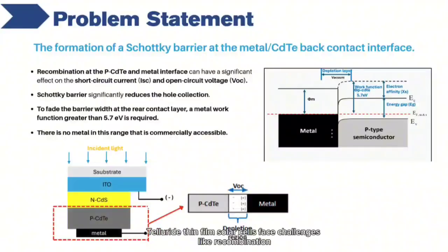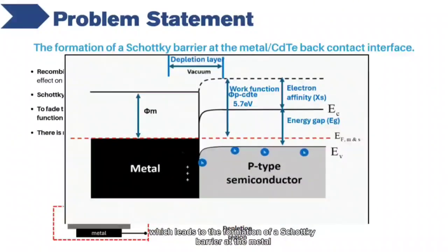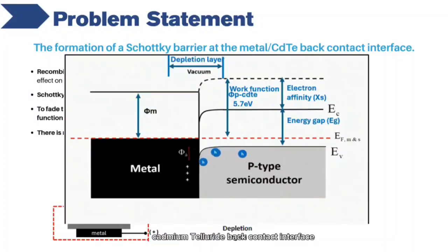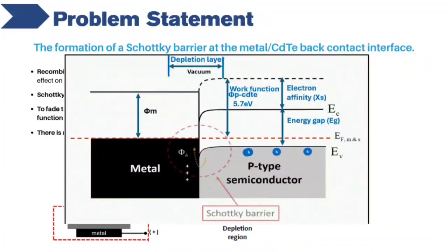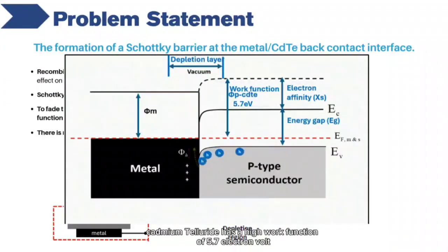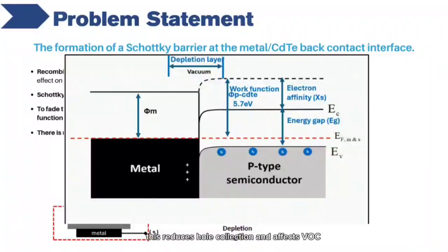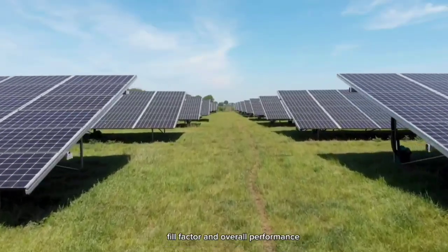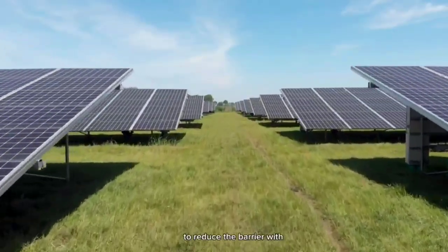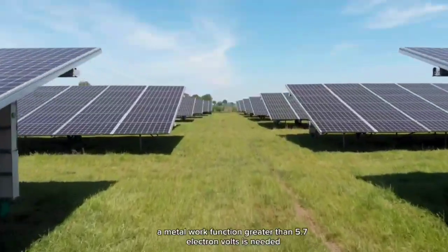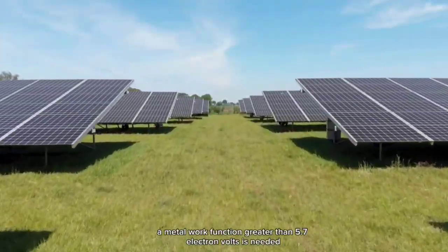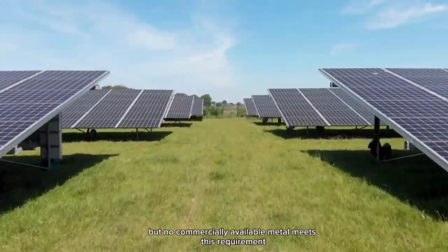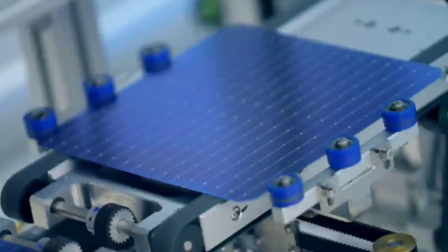Cadmium telluride thin-film solar cells face challenges like recombination, which leads to the formation of a Schottky barrier at the metal-cadmium telluride back contact interface. Cadmium telluride has a high work function of 5.7 electron volt, which is higher than other metals, forming this barrier. This reduces hole collection and affects VOC, fill factor, and overall performance. To reduce the barrier width, a metal work function greater than 5.7 electron volt is needed, but no commercially available metal meets this requirement.